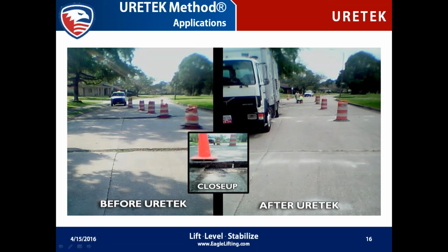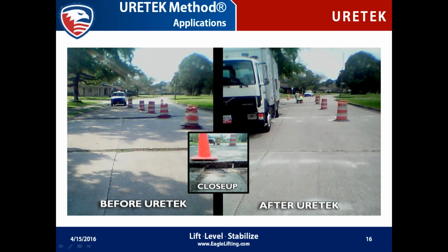Another great example is concrete pavement systems, using stabilization and lifting of dips and faulted joints. This includes concrete pavement systems that have a drainable base, which you can see here in the picture, the close-up of the faulted joints. This is actually rather severe settlement. And then after the injection of the structural polyurethanes, that gap has been closed.